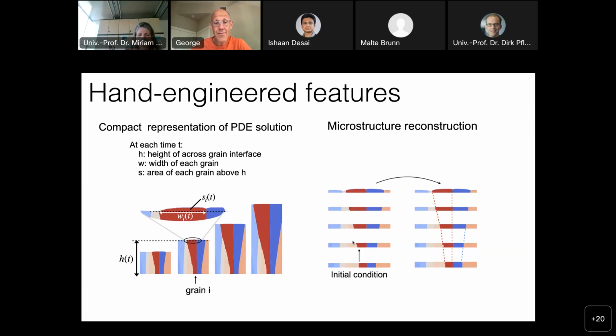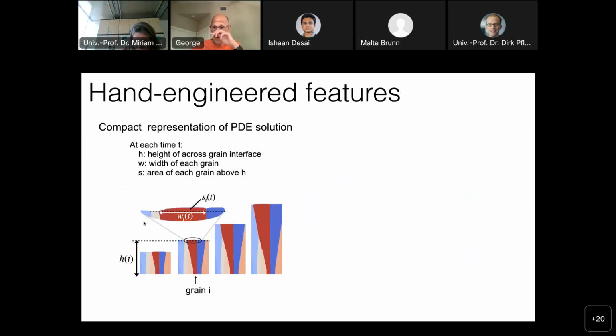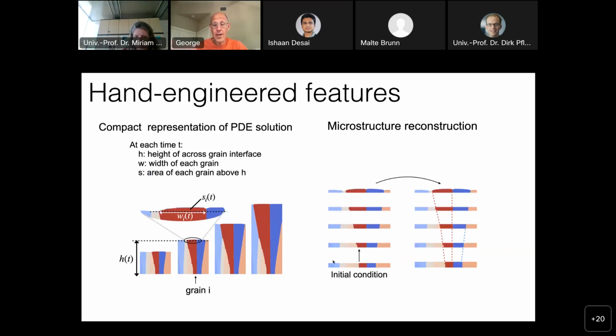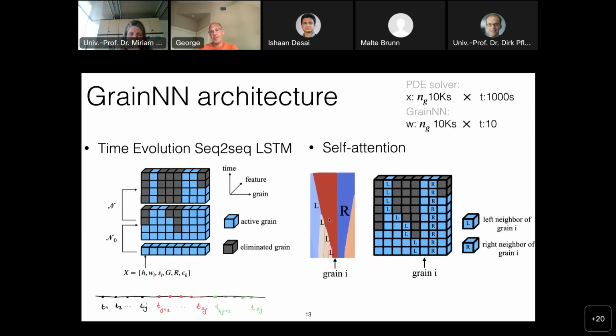And now once we have that, you can actually reconstruct. So imagine that if this is my initial condition, and these are these features at different time snapshots, we can have a reconstruction, let's say by linear interpolation, in which from these snapshots, we can go back to the original microstructure. So there's a way to go back and forth between these manually handcrafted features that compress the phase field representation and the actual phase field representation. So these are our manual features, and now our goal will be essentially to predict these features at every time step. So we're going to be running a forward simulation, we're going to extract these features, and then we're going to try to predict them using the reduced order model.